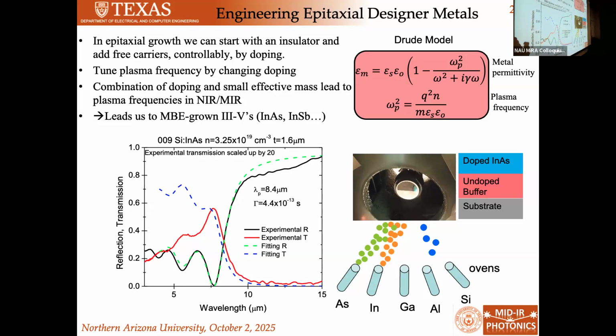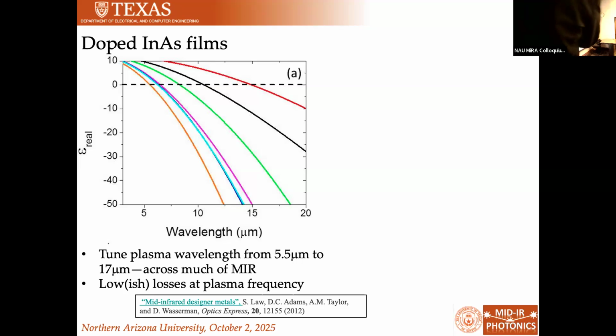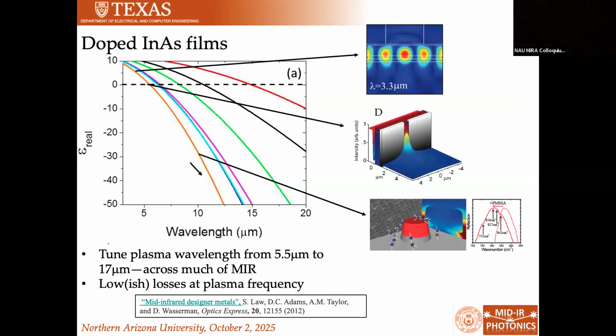So we can basically make our own metals in our epitaxial system, where we have atomic-level control of thicknesses, and we can control to our heart's desire the amount of free carriers that we put into these materials. This is the same basic material, indium arsenide in this case, and we can tune the plasma wavelength, the region where our permittivity crosses zero, across the mid-infrared, right? Now what this does is it gives us a material system where we can go from, for instance, a low-index material to an epsilon-near-zero material, all the way to a plasmonic material, right? And we can do that as a function of wavelength, or we can control the doping, and we can shift that as well.